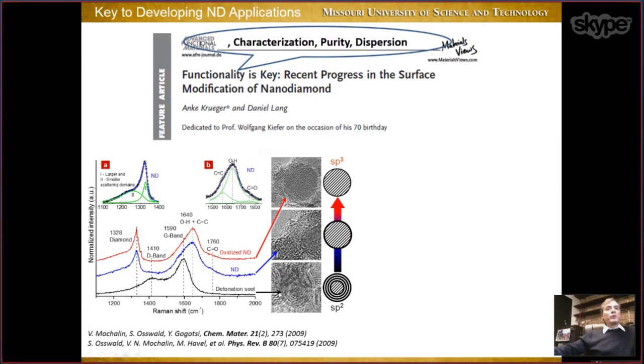Okay, but then if you put it under transmission electron microscope, you would understand why you don't see diamond peak here, because your diamond core is engulfed by layers of graphitic carbon, and there's a lot of amorphous carbon around. So basically your diamond core is heavily shielded, and you simply cannot see Raman signal from it. Okay, if you purify it, then you get less graphitic carbon, and you can again see it clearly under TEM